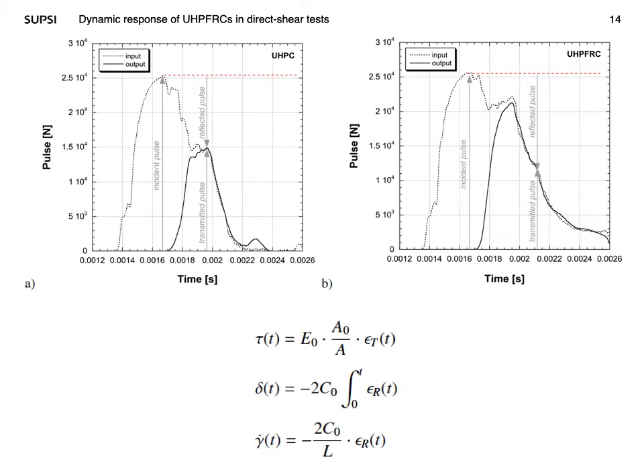As you can see in the slide, it's possible to obtain a very clean resolution of incident, reflected and transmitted pulses, a sharp rise time of incident pulse around 200 microseconds, and lastly, the constant amplitude of incident pulse. On the basis of this material and considering the equation regarding the one-dimensional wave propagation, it is possible to evaluate the shear stress, shear slip, and strain rate history. In this slide,